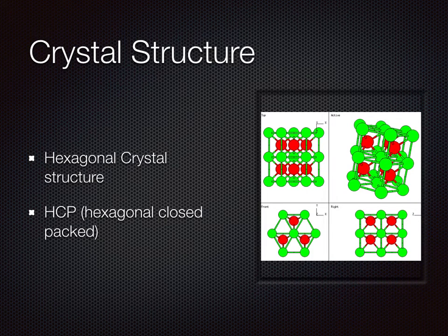Now let's talk about the crystal structure. Tungsten carbide has a hexagonal form that can be visualized as made of a simple hexagonal lattice of metal atoms of layers lying directly over one another, with carbon atoms filling the interstices, giving both tungsten and carbon a regular trigonal prismatic coordination. This structure is similar to the hexagonal close packed that we learn in school. However, the c/a ratio in tungsten carbide is about 0.98, while typical HCP material is about 1.63.